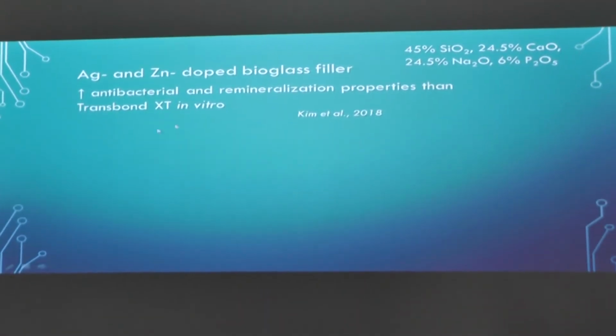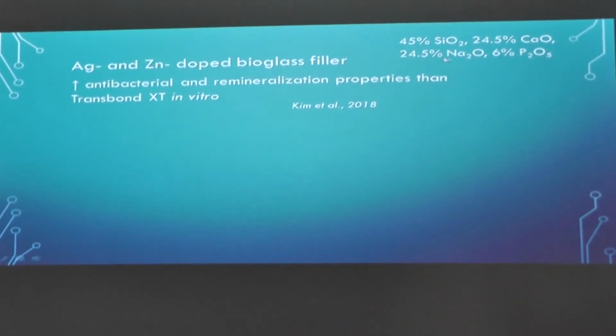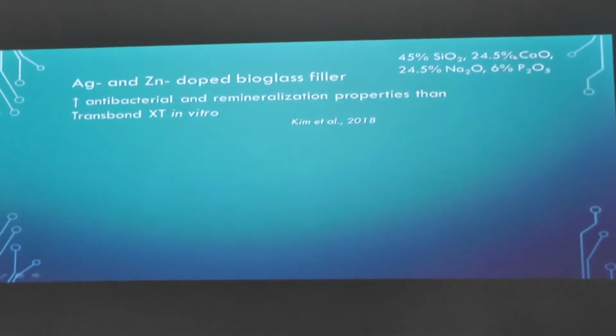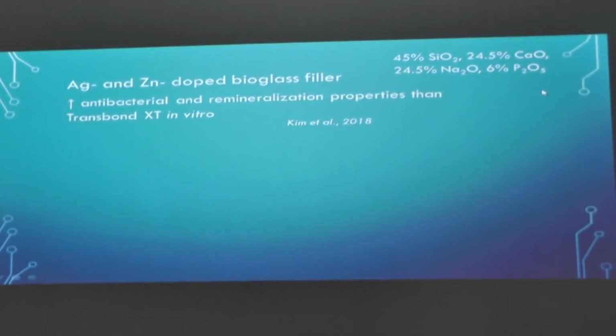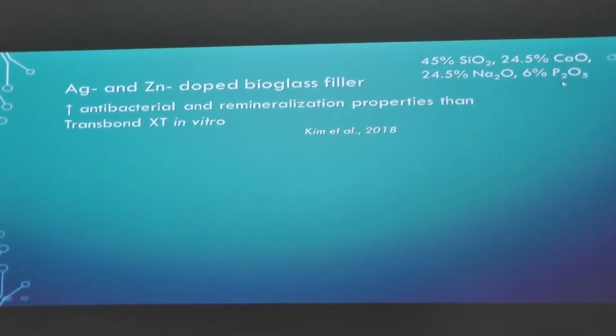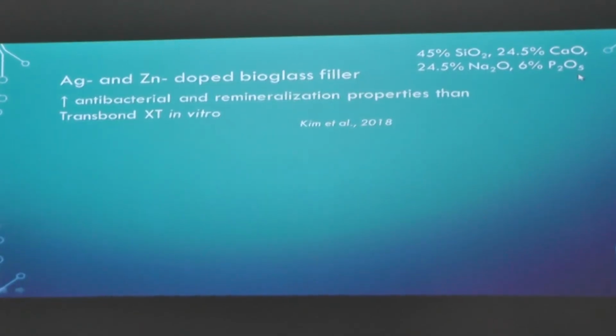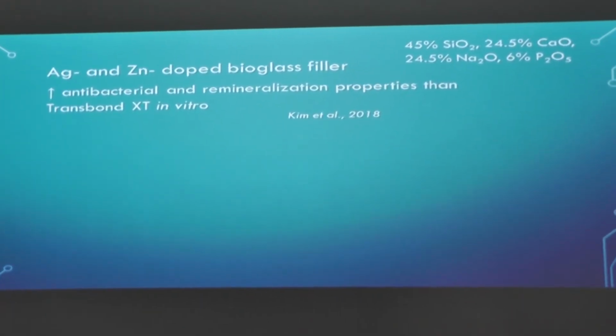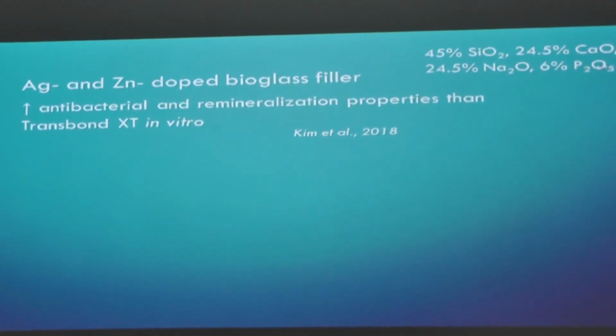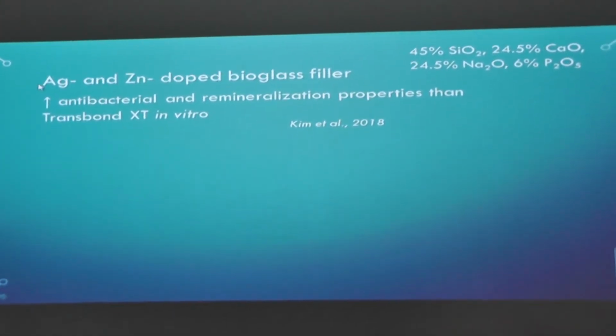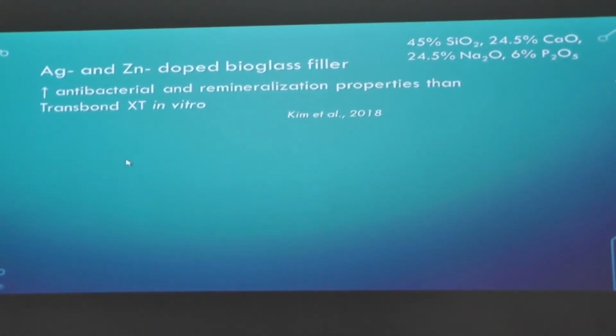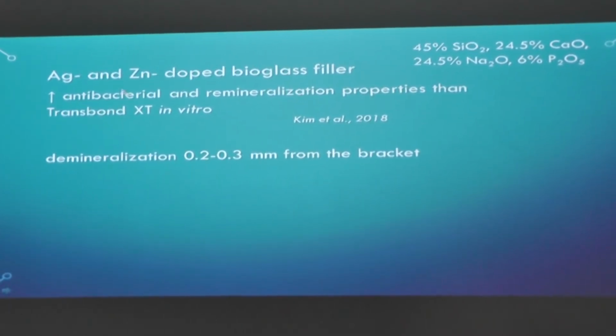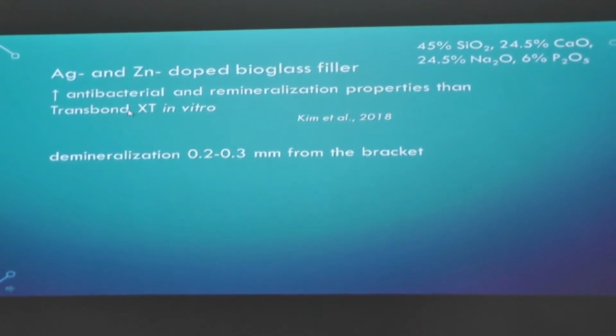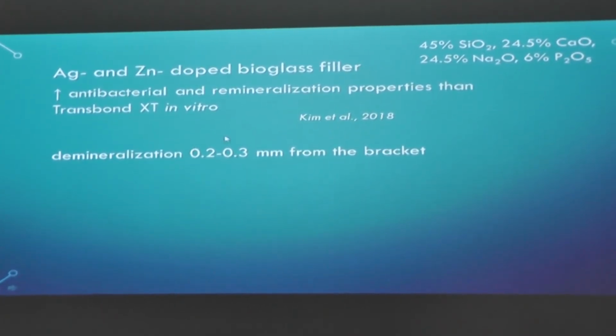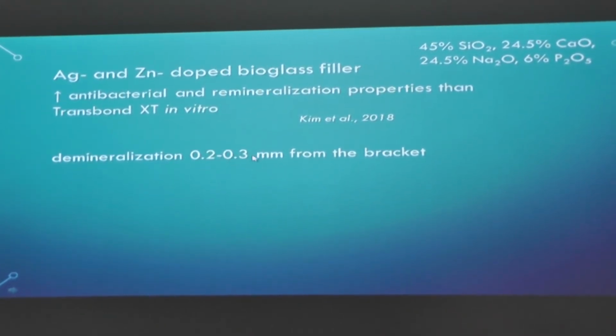And this is a recent study that I found that used a BioGlass filler. This is the BioGlass used in oral surgery also, the same one, which has osteoinductive, bioactive properties. This can induce the spontaneous formation of new hydroxyapatite prisms, because it contains calcium and phosphate ions. And they added silver and zinc to increase the antibacterial activity. And they found that it has superior properties than Transbond in vitro. So Transbond showed a demineralization immediately next to the bracket, while in the case of their tested material it was 0.2 to 0.3 millimeters away from the bracket.